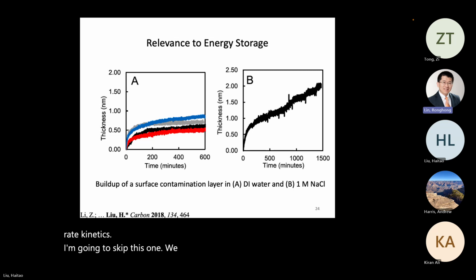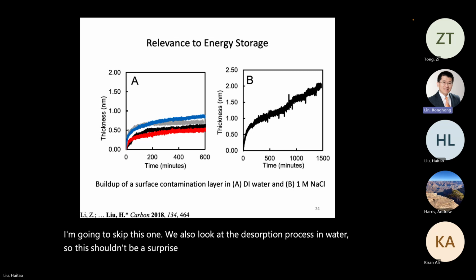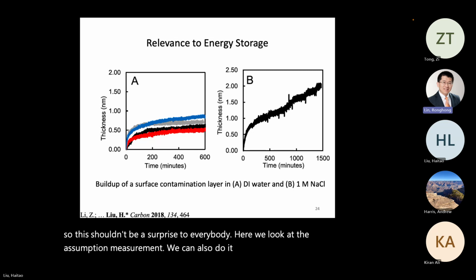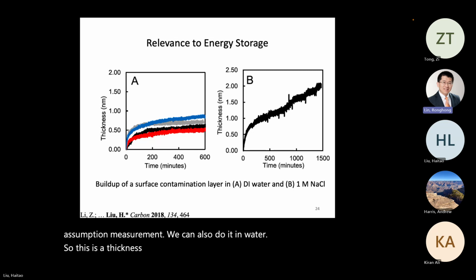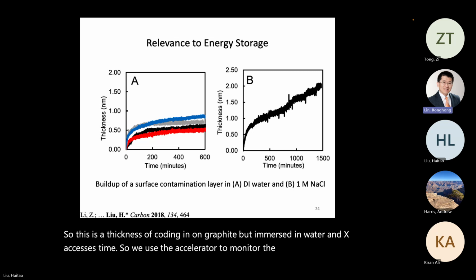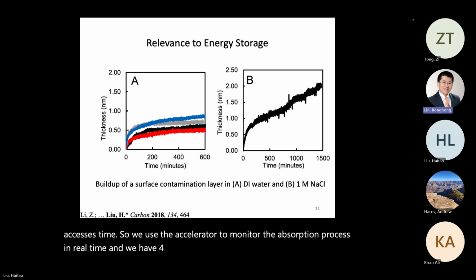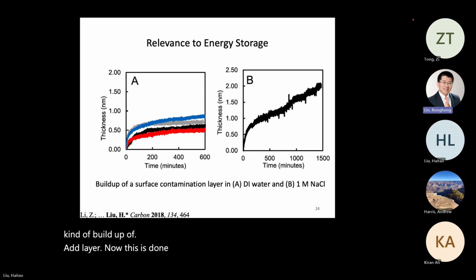We also look at the adsorption process in water. This shouldn't be a surprise to everybody here. We look at the ellipsometry measurement. We can also do it in water. So this is the thickness of coating on graphite, but immersed in water, and the x-axis is time. So we use ellipsometry to monitor the adsorption process in real time. And we have four different samples, and all of them show some kind of buildup of an adlayer. Now this is done in nanopure water.